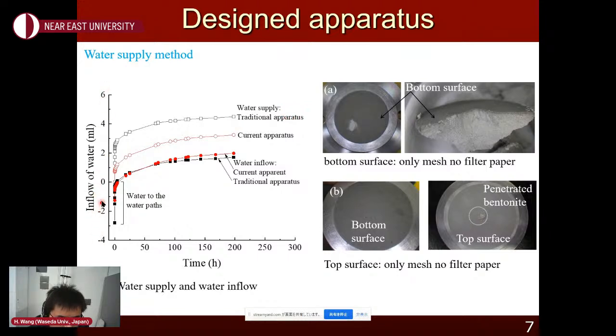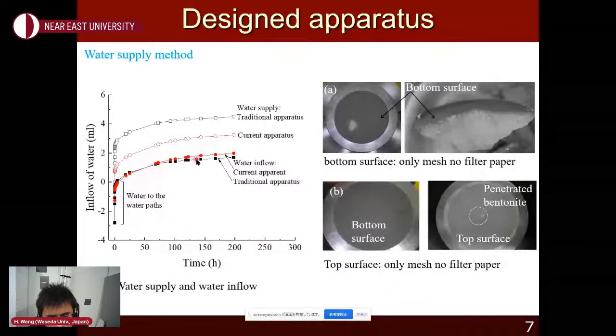The vertical axis is the inflow of water, so the amount of water supplied to the apparatus. And another, this red one, is the current system. This water does not all flow into the specimen because there is some space in the water flow path. We try to estimate the water path space, subtract this space, and get the water that actually flows into the specimen. As you can see, these two curves, with the traditional way and our way, are very similar.